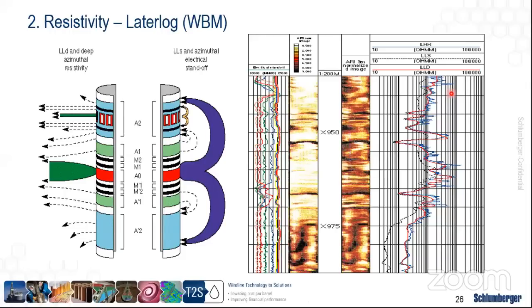The second type of tool that we have is that, to further elaborate on this, as I said, we emit very high current output that goes deep into the formation, and it's detected at multiple receivers across the tool body. Due to this interaction, we can estimate and measure the current or the resistivity at each and every investigation. And by measuring the voltage drop, we can compute the resistivity of the formation.